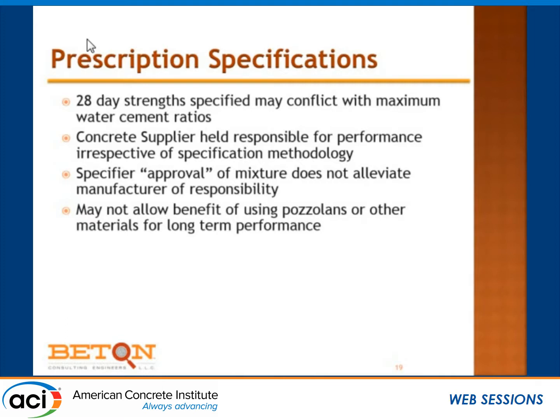And the other is that it prevents us many times from using pozzolans or other materials for long-term performance. For example, 318 has a restriction on the pozzolan content, concretes that are exposed to freezing and thawing. And they're trying to protect the concrete from scaling, which is a superficial loss of the paste. The code, people will tell you, is designed as a minimum life safety.